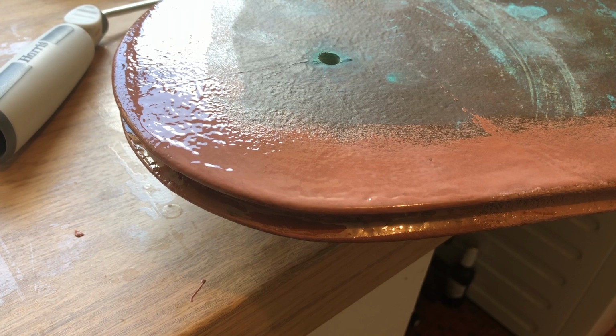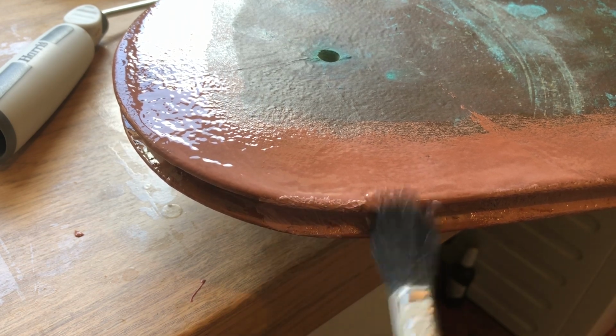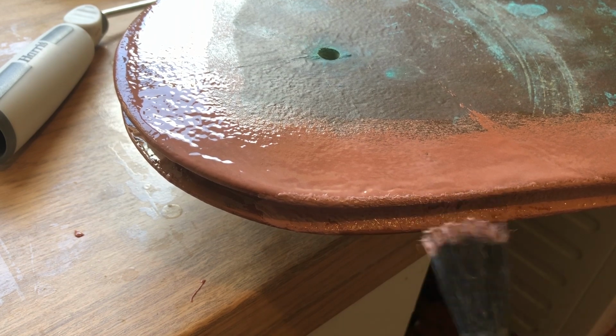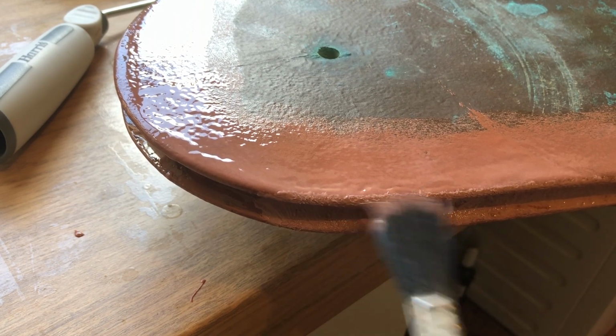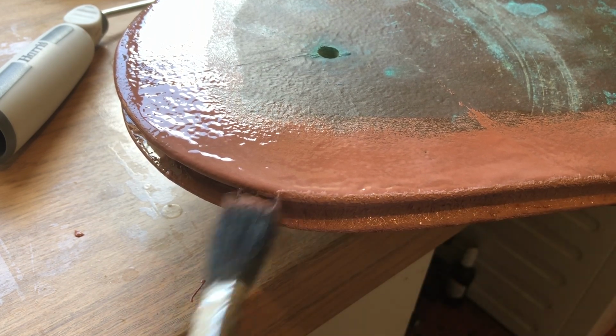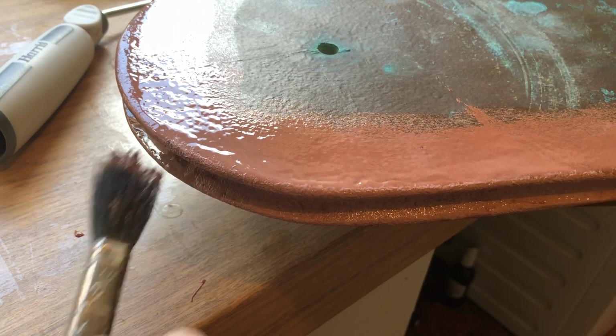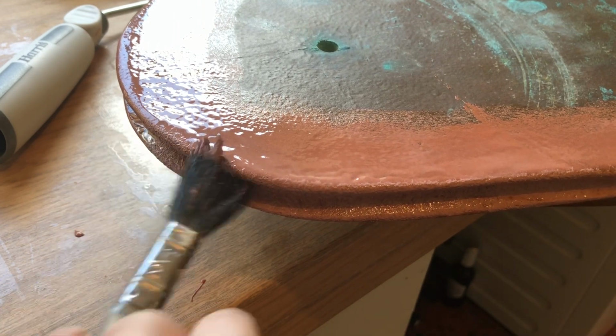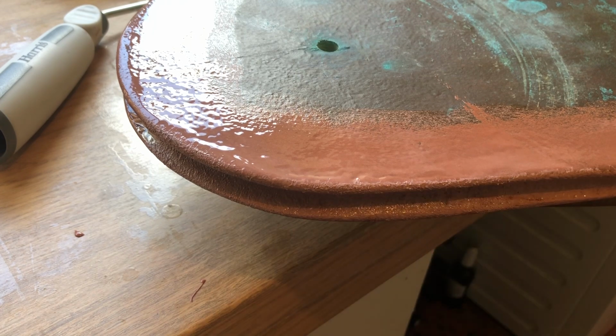An elasticated cord holds the rudder blade in the down position. This sits in a groove at the top of the blade. I couldn't get the roller inside the groove far enough to apply sufficient Coppercoat. Dabbing with a brush worked really well. You're not supposed to brush Coppercoat, but dabbing into the groove applied the Coppercoat as if using a roller.